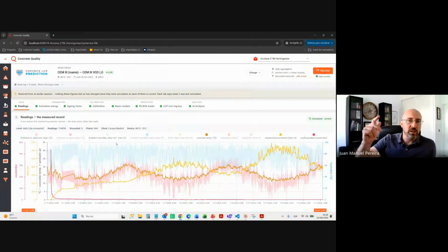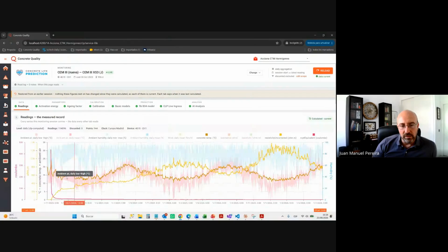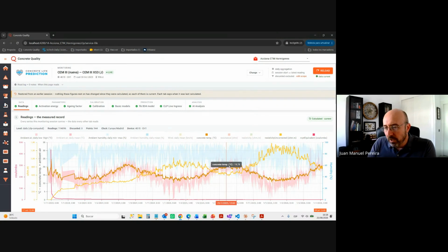If it's raining, if it's sunny, the wind, etc. What you see here is the pink outline, the ambient temperature, max and min. This here is the temperature of concrete, and this is the electrical resistivity. You see this effect: when the temperature goes down in the winter, electrical resistivity goes up, meaning it's harder for the chloride ions to move through the concrete. This is the same for carbonation in a carbonated exposure. Then in the summer the resistivity goes down, but it has this trend.